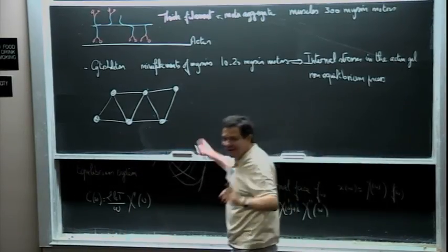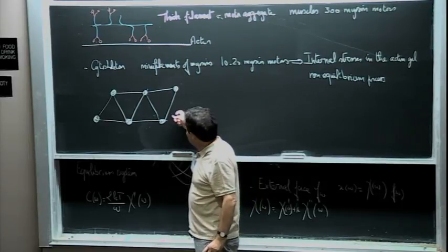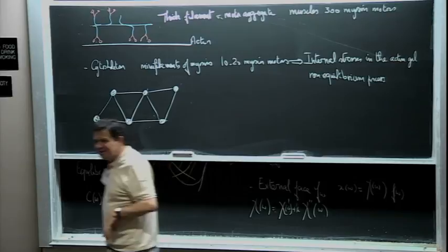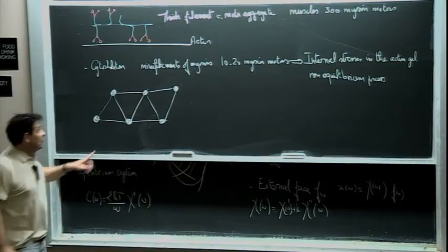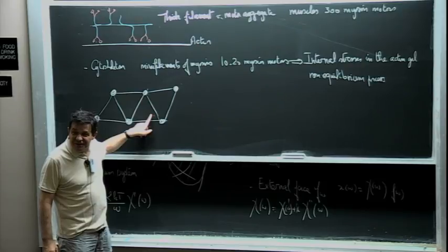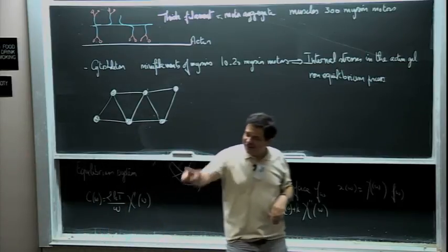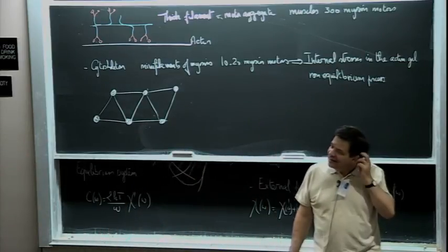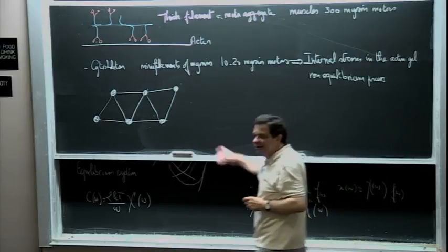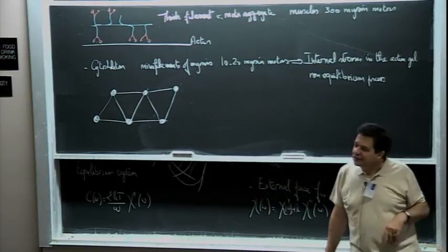I don't know how to answer, but the way we did it, at least, you have a violation of the fluctuation dissipation theorem only if the spectrin network is pre-stressed, which means the violation is proportional to the pre-stress of the spectrin network. So the springs are under tension, if you want, which is not exactly the same thing as what you say. But in our system, it's required that the springs are under tension, which was kind of known.